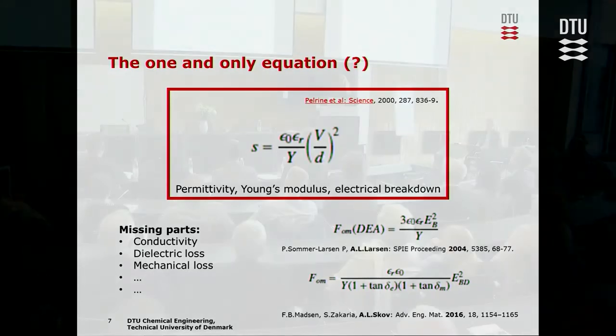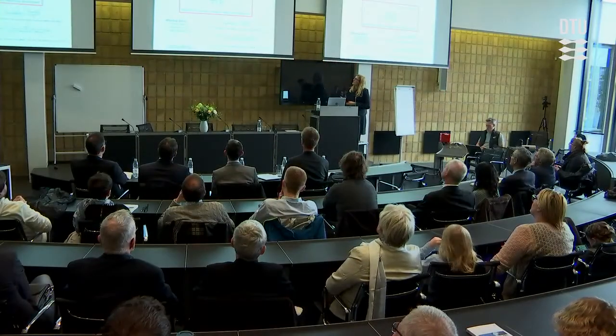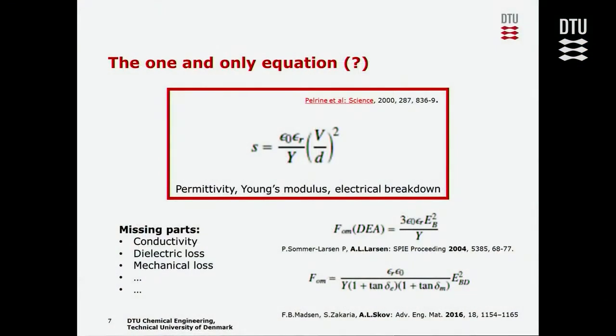In 2004, together with Peter Sommer-Larsen, we derived this figure of merit for the dielectric elastomer actuator material, where we coupled the dielectric permittivity over the Young's modulus multiplied by the electrical field squared. But this equation somehow forgets a lot of important parameters for our dielectric elastomer performance. For example, I think the most important is, do we have conductivity in our material? Because then we don't really have a dielectric elastomer. Actually some of the materials that have been shown as dielectric elastomer prototypes have shown conductivity, which means over time we will see the material leak a lot of current.